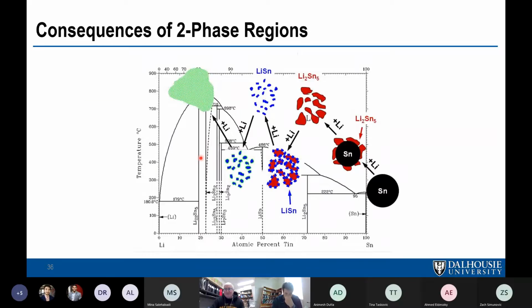And this slide illustrates the problem with 2-phase regions in the case of tin, because there's more 2-phase regions here. So it magnifies the problem. If you have a particle and you're lithiating it electrochemically, of course, the lithium is coming from the surface. And so the first thing that you lithiate in a 2-phase region is the surface. If you're starting with pure tin, you start lithiating it, you're going to enter this 2-phase region, and on the surface, you're going to form this phase. And you can see it formed here, and you just get more and more of it, and the tin phase is consumed at the expense of this one as you add more lithium. This phase is about 100% volume expansion compared to tin, so that causes a lot of stress, and you get cracking and fracture until you completely lithiate it. And again, things are growing here, so typically during lithiation, everything's under compression, so even though they're fracturing, they stay together. And if you lithiate more, then you enter another 2-phase region, and that makes more.